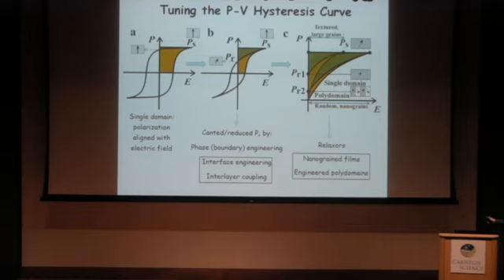But if you have a polydomain structure, which has a head-to-tail configuration of domains, and this polarization is canted to the applied field, in the remnant state you will have apparent zero polarization to begin with. And when you charge this film, of course, one set of the domains will be favored, but this is at the cost of removing the domain interface. So it's very difficult to saturate. At the same time, if you discharge, because the head-to-tail remnant configuration is stable, you can get close to zero remnant polarization. So this kind of structure is very good from a dielectric capacitor point of view.